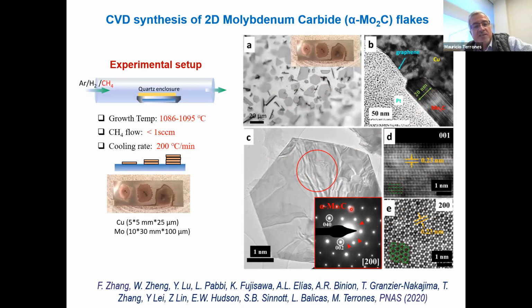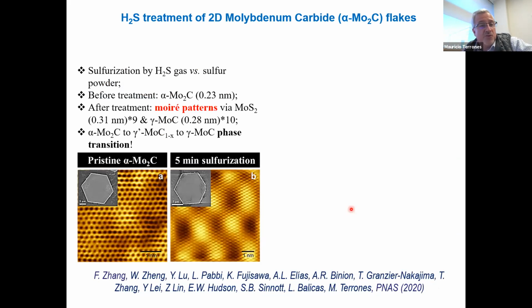So now the idea is, can we transform these crystals, or partially transform these crystals, into moly sulfide? And this is what we did. We did sulfurization with H2S gas or sulfur powder as well. So you have the pristine hexagon platelet, and after you sulfurize it, you see the hexagon is preserved. But when you do STM on this alpha moly carbide, you see a sort of moiré pattern, which I will tell you about, but it's the stacking of the moly sulfide with the moly carbide.